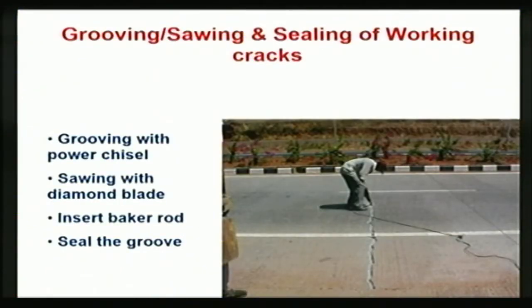This is another way of cracking. If you do not do the sawcutting at proper time, then you will observe that a full width and full depth transverse crack will appear at an interval of 10, 12 or 15 meters. Those cracks are called working cracks, because those are not structural cracks. Though it is full depth and full width, it is not because of the structural failure of the concrete. It is occurring because you could not cut the joint at proper time with proper depth.